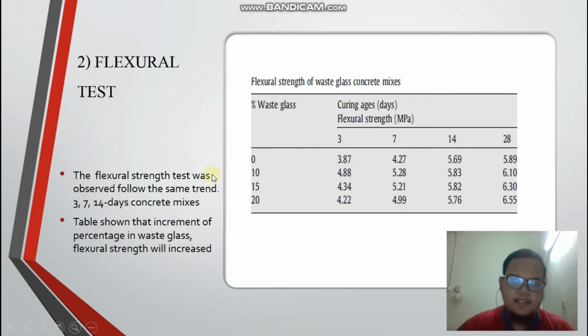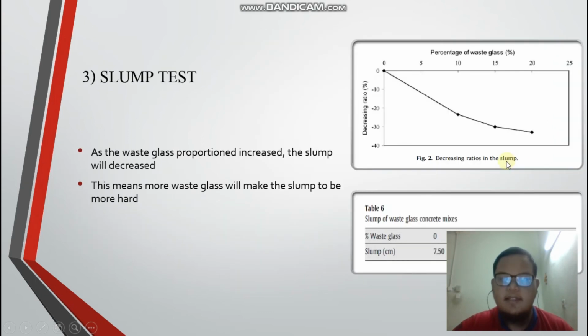The next one is the flexural test. The flexural tests are presented in the same pattern, at 3, 7, 14 and 28 days. As you can see here, at 20% waste glass, it also increased from the plain mix. And the last one is the slump test. However, for the slump test, with an increase in the percentage of waste glass, the slump decreases, which means the concrete mix might not be workable.